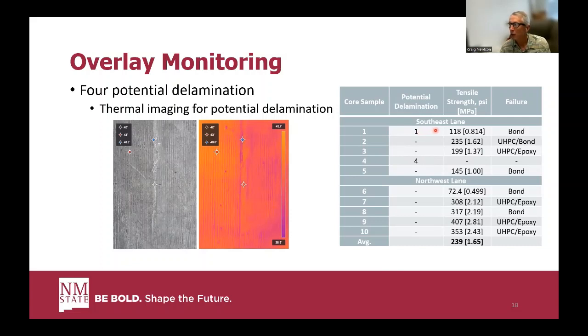Area number 1 didn't meet minimum strength, but it was not a 0 strength. It was not completely debonded at that location. When we look at the average strengths, we were happy with what we got there in terms of the bond strength between the UHPC overlay and the substrate. So by and large, it looked good.